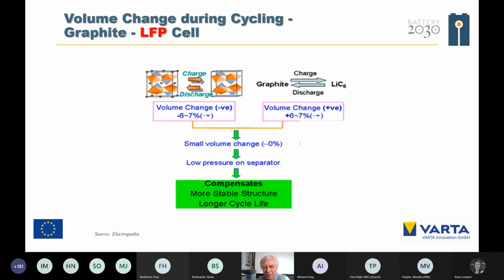So let's have a look at the volume changes during cycling of conventional batteries, the LFP battery. In the LFP you have a volume change during charge and discharge of about -6-7%, and on the graphite electrode you have a volume change of +6-7%. So you have practically no volume change. So you have low pressure on the separator, a very stable structure in the LFP, and you have a longer cycle life in that case with LFP batteries.